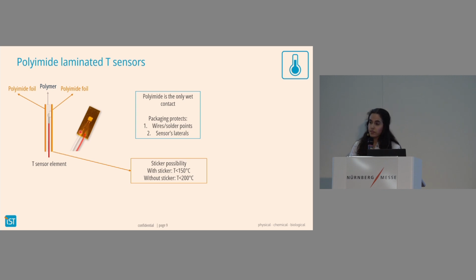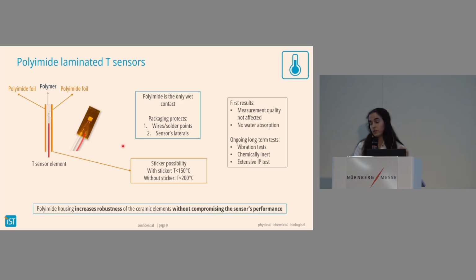We have tested this with the possibility of sticking it directly. In this case, the temperature can go up to 150 degrees, and without the sticker, it can go up to 200 degrees. So the first results have shown that the measurements of the temperatures are extremely precise. So basically, we measure pretty much as if it was without this extra layer of material, and there is no water absorption. And further tests that we are doing are vibration tests, chemical inertness tests, and extensive IP tests, and these are also so far quite good.